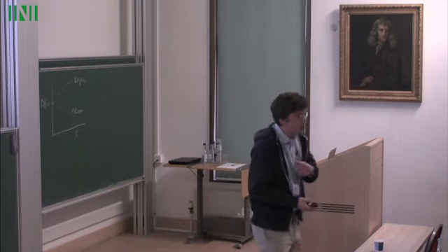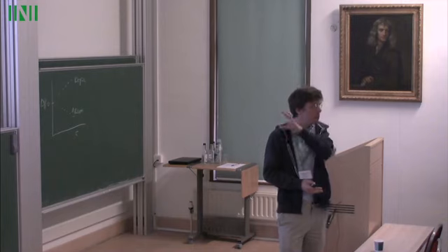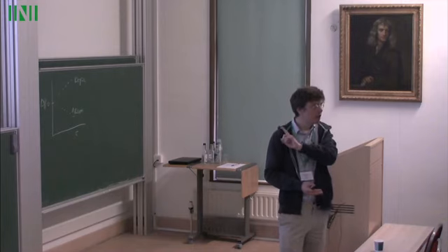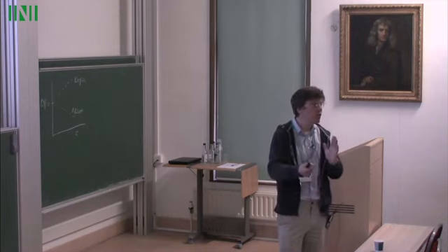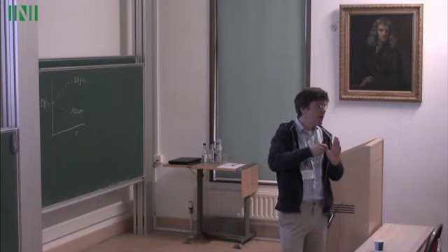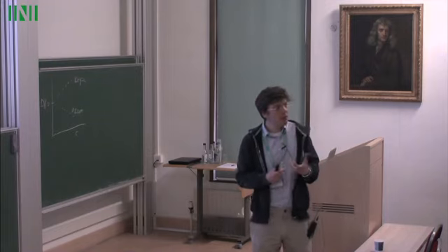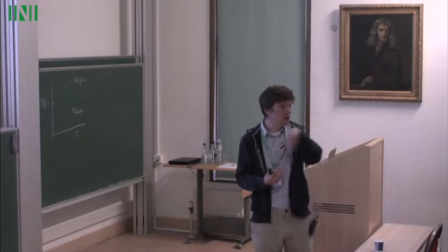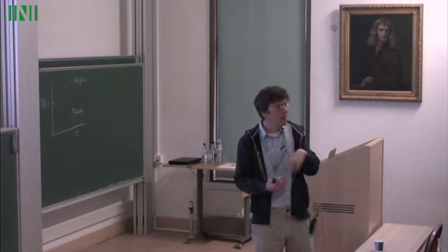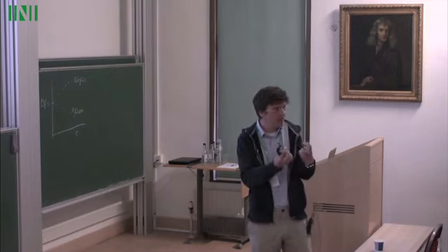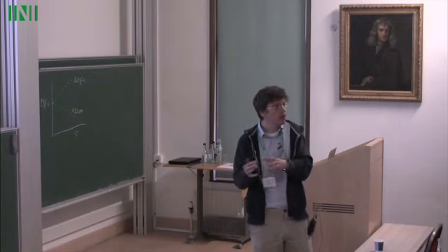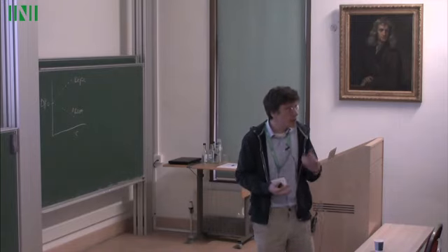What is very nice is that if you do the optimization in bulk, it still reproduces the surface properties, even though this polarizability is not explicitly included. I would say it is implicitly included because we optimize the London part of the Lennard-Jones interaction. We change the Lennard-Jones parameters in bulk, and that should include at least part of the polarizability.